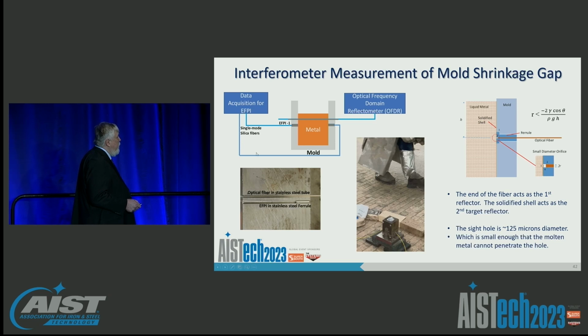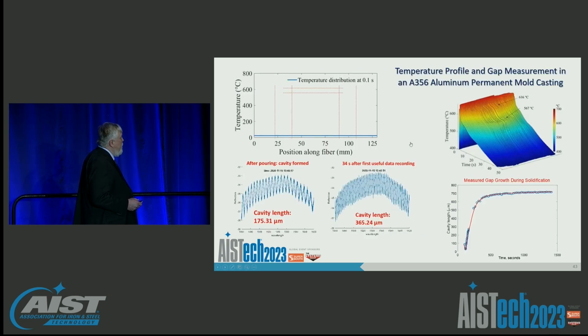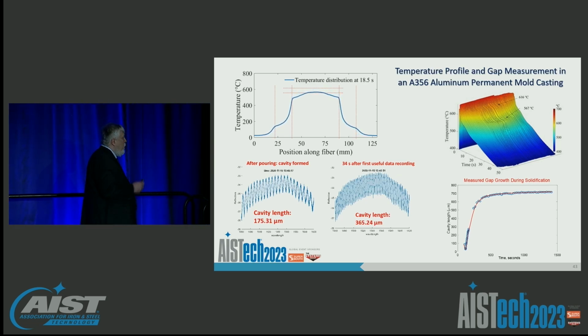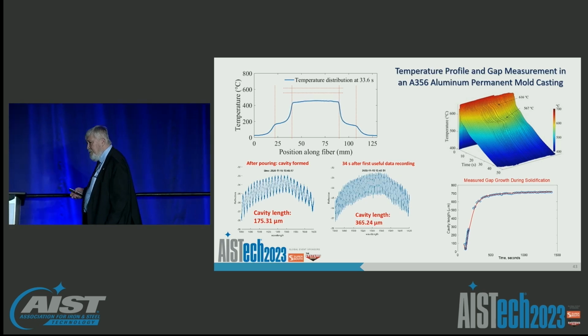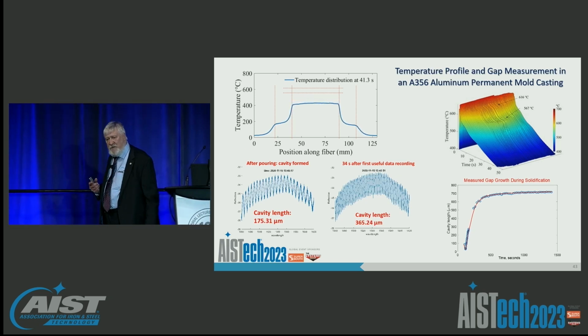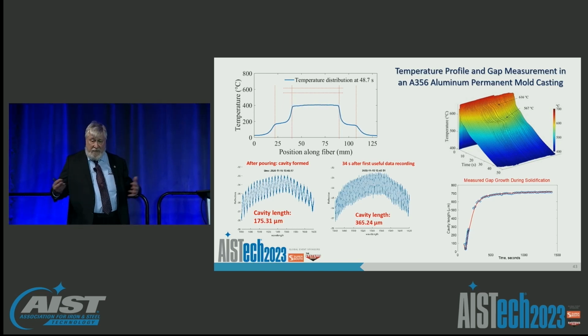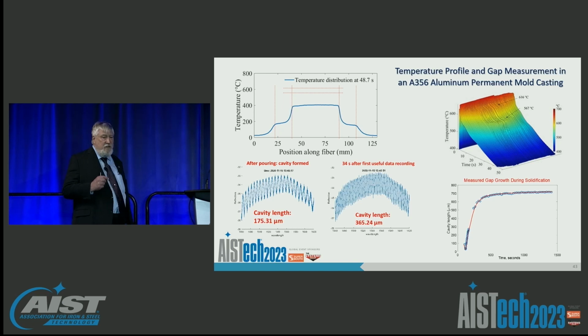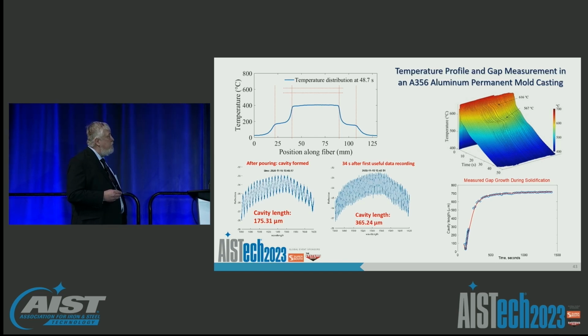So this just shows the interferometer setup and some other things, but here are actually some of the results. And if we combine it with some of the Rayleigh backscattering fiber temperature monitoring, we have all the information we need to monitor the thermal profile through the mold wall, through the solidification cavity, but also directly measure the evolution of the gap, which is a very difficult measurement to do. I know there are some people in the audience here who have done it with LVDTs or Temposonics. It's very difficult because you have to compensate for those temperature changes along the connecting points. Here, this interference pattern is temperature insensitive, so it's really a pretty benign sensor and gives you a lot of really valuable information.